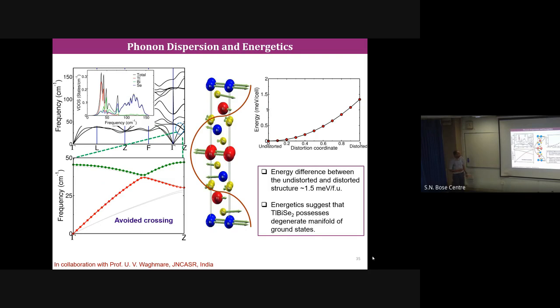So what we believe now, because we have seen the energies of the undistorted and distorted structure, is that the local distortion creates manifold degenerate local minima. And we believe, we don't have the proof right now, that the structure hops from one minimum to another, and that's why the compound has such low thermal conductivity. And we believe if you can create more and more minima, one can have a glassy-like thermal conductivity. We have seen this in another compound. This compound shows crystal-like thermal conductivity.